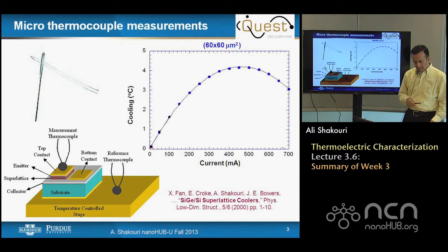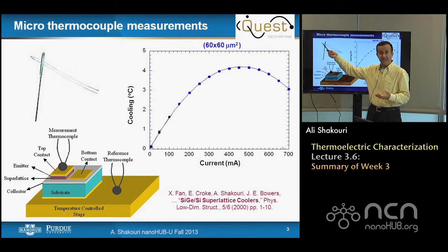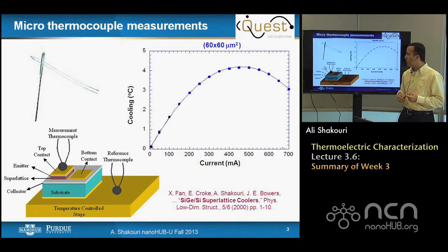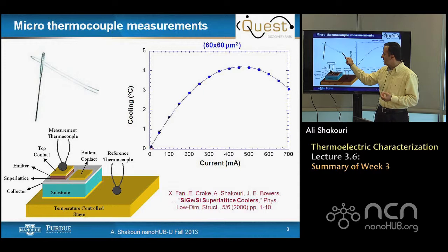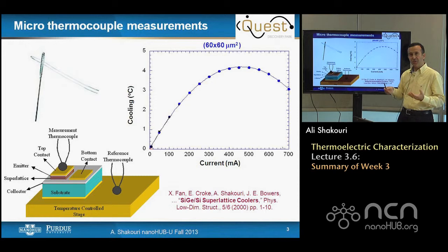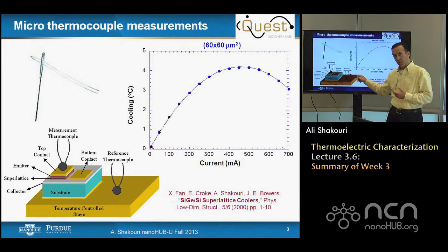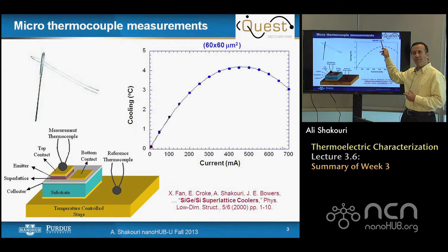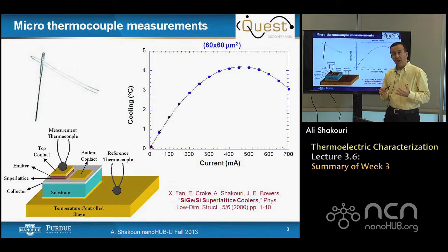The simplest way of measuring temperature is a micro-thermocouple — tiny devices based on the Seebeck effect. Two legs with two different metals with different Seebeck coefficients: when one side is hotter, it generates a voltage and that's our thermometer. You need to ensure the other side is isothermal with no additional temperature differences, as those introduce spurious signals. Using a differential thermocouple measurement, you can measure temperature at scales of a couple of tens of microns with precision of 0.1 degrees or lower. Thermal contact between the thermocouple and the object is important, especially if the object is the same size as the thermocouple, so thermal grease is often needed.